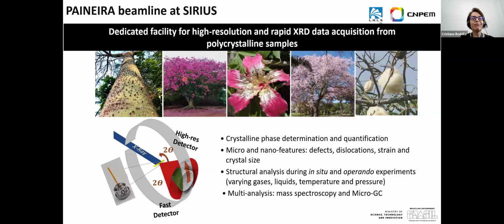experimental hall. So Paineira is a dedicated facility for high resolution and fast XRD acquisition to study polycrystalline materials. There you can determine and quantify crystalline phases. You can study micro and nano features of your crystal, such as defects, dislocations, strain, and determine the crystal size.